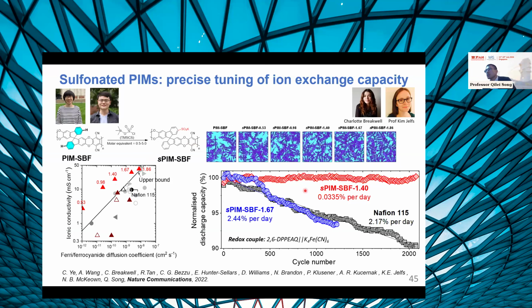And also the optimal membrane, for example, with an ion exchange capacity of 1.4, gives much more stable battery performance. But of course, if you increase the ion exchange capacity, if you have a relatively higher degree of sulfonation, the polymer will swell, and you can see the decay of the battery.